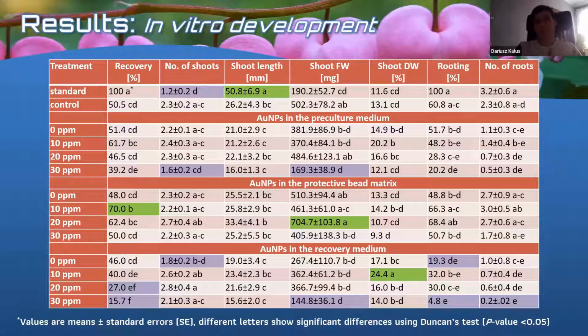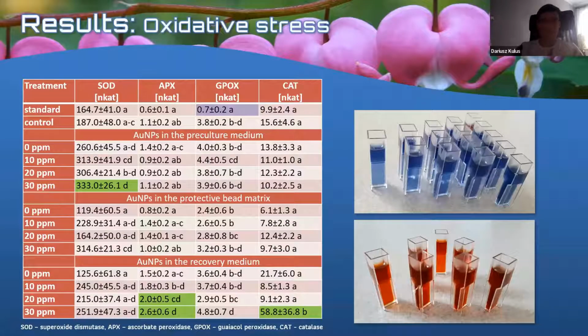And also the addition of nanoparticles did not affect the elongation of shoots. Again, we observed that the shoots that were produced after cryopreservation in general were shorter in comparison to the in vitro grown control. That's because of the alginate capsule, which inhibits a little bit the growth of the shoot tips, and here also the nanoparticles did not affect those events. We also studied some oxidative stress events in the cells by verifying the activity of 4 different enzymes, and we found that, as it was predicted, the addition of nanoparticles did affect the oxidative stress in plants.